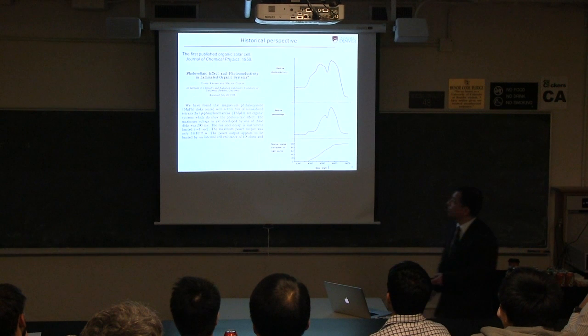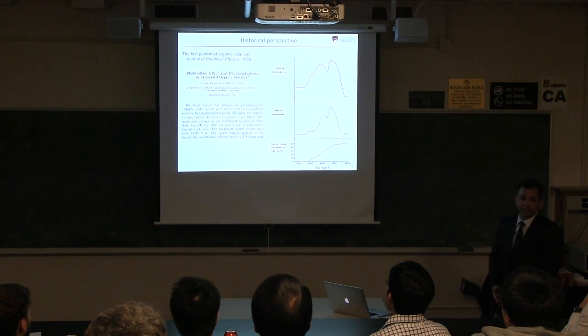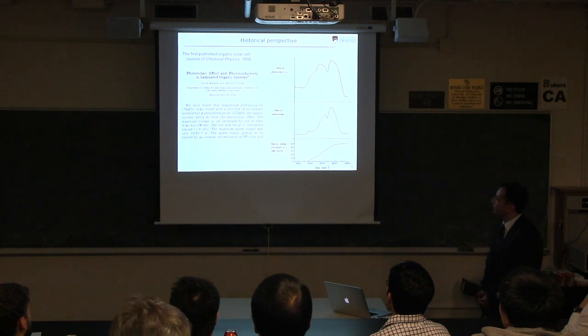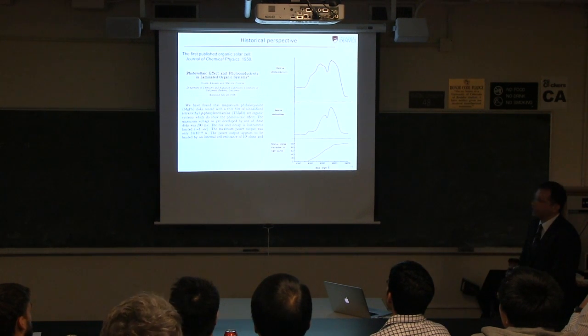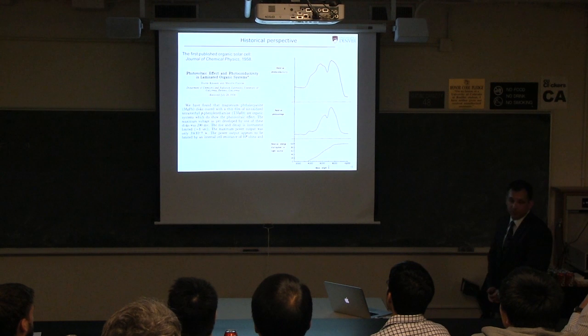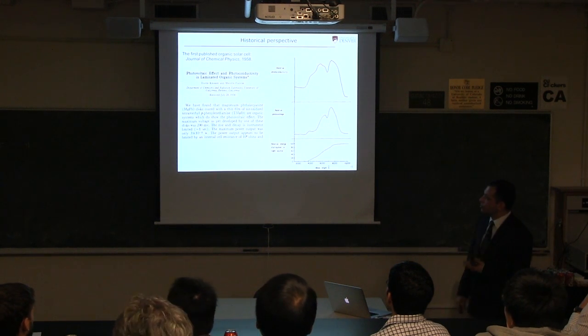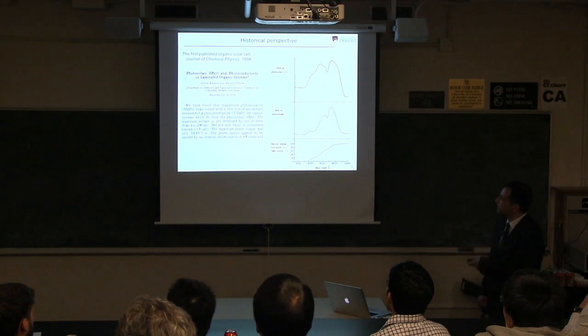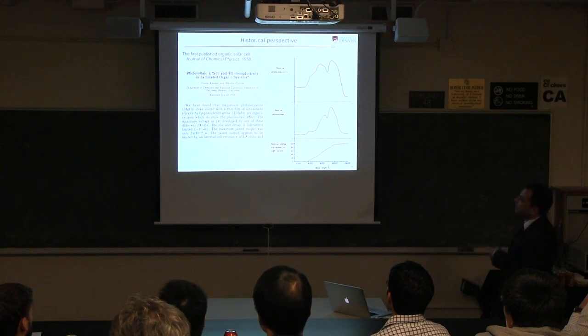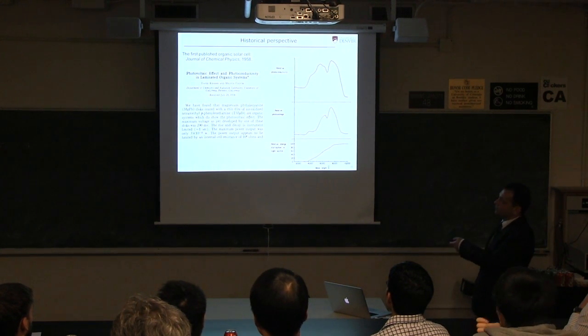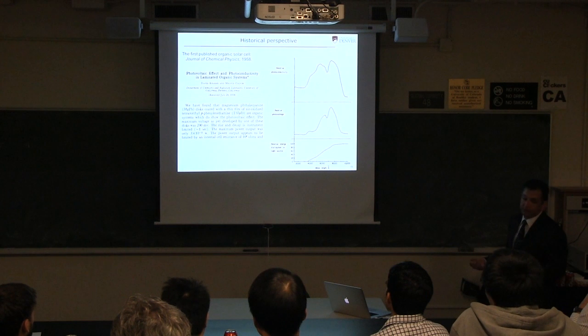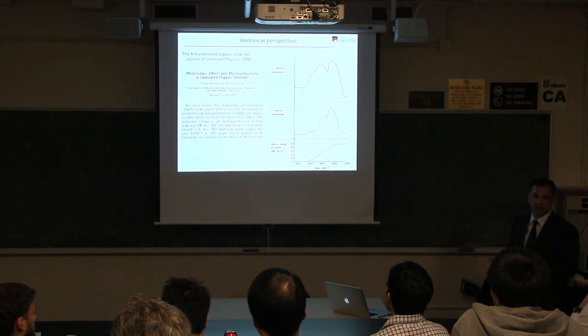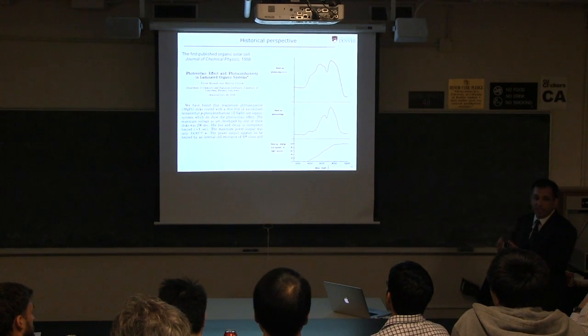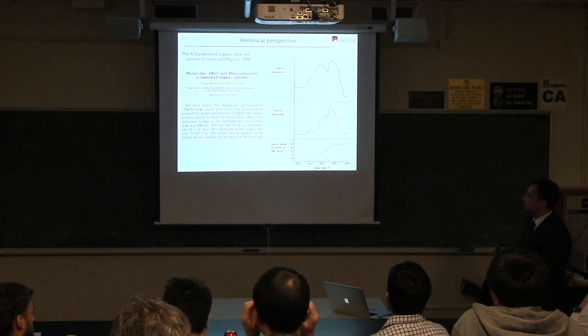So a little historical perspective. OPV is actually an old field. The first published paper was in 1958. It came out of Berkeley, from David Kearns and Melvin Calvin. And it was a pretty cutting edge device. First of all, it used 2 different organic semiconductors, magnesium phthalocyanine and also tetramethyl phenyldiamine. And in fact, that's what we do today. We use 2 organic semiconductors to ostensibly break up the exciton, the excited state in the devices.